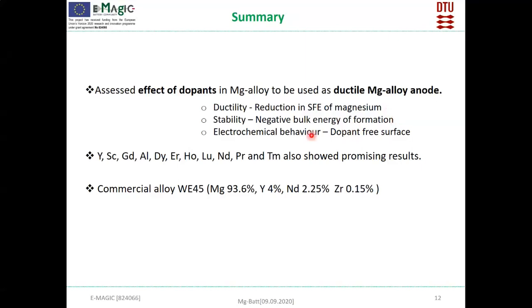Then we studied the electrochemical behavior. When I say the electrochemical behavior, we look at whether we can obtain a dopant-free surface for these alloys. So after evaluating based on these criteria, we got almost 11 dopants which show promising results. Out of that, aluminum is the only non-rare element, the rest of the elements are rare.